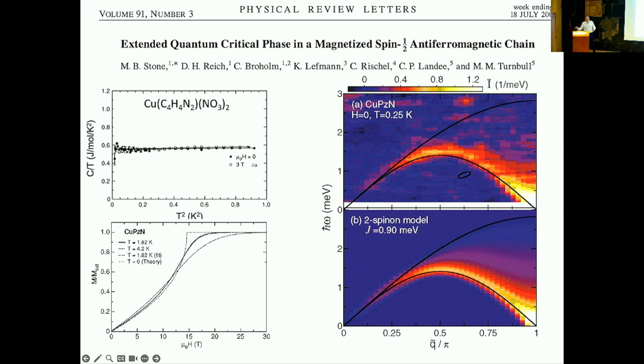Okay, I briefly want to show you the magnetization curve for this material. So this is magnetization as a function of applied magnetic field. When we come up to around 20 tesla, we have fully saturated the magnetization of the spin system. But you'll notice it's a completely smooth curve. There's some interesting behavior happening at the highest field, but otherwise a pretty smooth curve. This will juxtapose with, and will be quite different from, the materials that I'm later going to show to you.